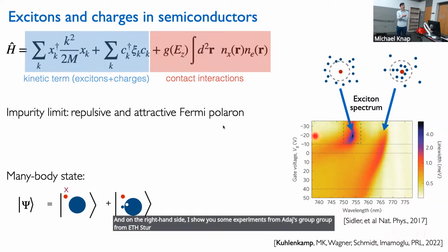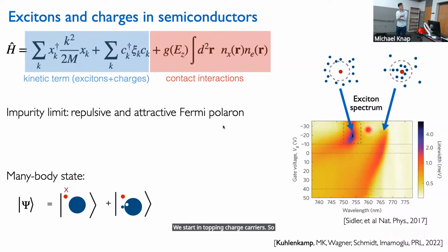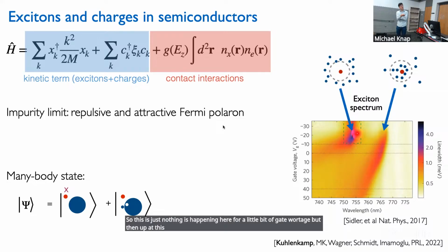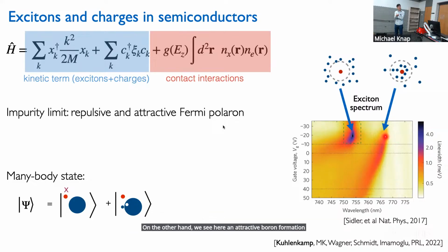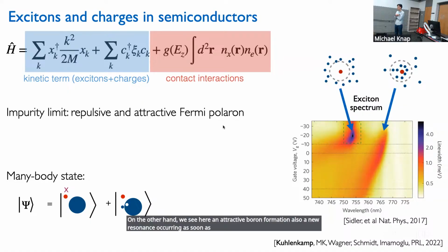where they actually now tune the gate voltage. And when you go down here, we can focus on the upper part of this plot for illustrative purposes. We start in doping charge carriers. So this is what you can see here, the bare exciton line shape. So nothing is happening here for a little bit of gate voltage, but then at this point, a shift occurs to lower wavelengths, so higher energies, which is the formation of the repulsive polaron. On the other hand, we see here an attractive polaron formation, also a new resonance occurring as soon as we have charge carriers in the system. Okay, so that's what we have here.